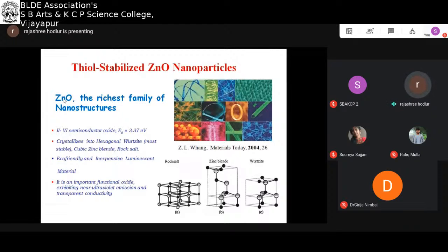This is a metal oxide semiconductor with a wide band gap of 3.37 electron volt, and mainly the three possible crystal structures of zinc oxide are the hexagonal wurtzite, the cubic zinc blende, and the rock salt. Under ambient conditions, one can obtain the hexagonal wurtzite. But the other two are obtained only under very extreme conditions. Obtaining the rock salt crystal structure is practically not feasible under normal conditions. The importance of this metal oxide semiconductor is that it is eco-friendly and inexpensive. It is a luminescent material, and an important functional oxide exhibiting near ultraviolet emission and transparent conductivity.